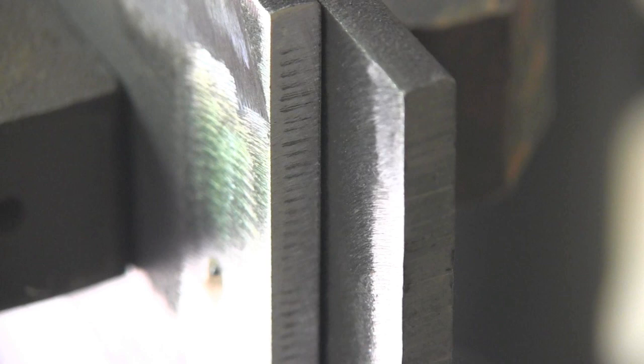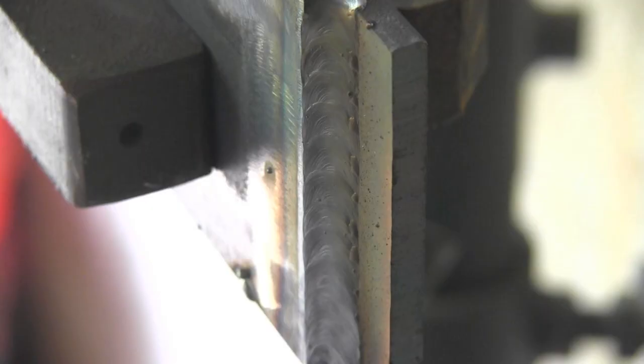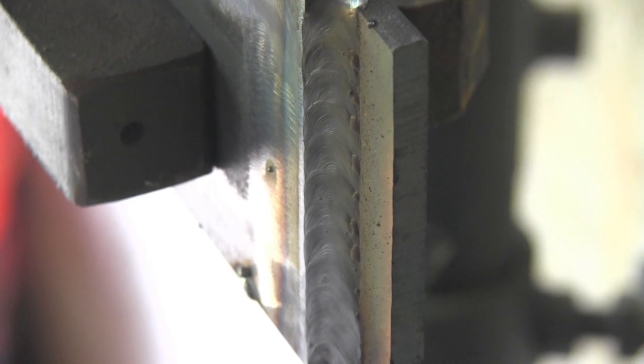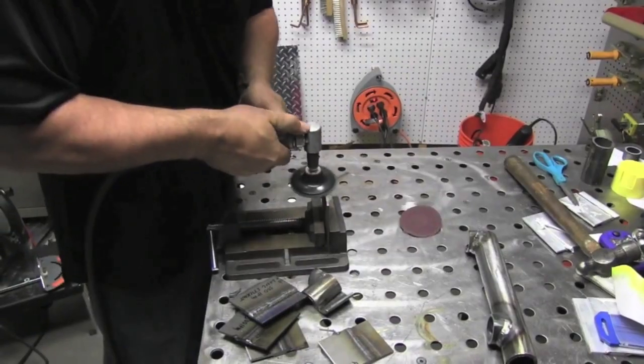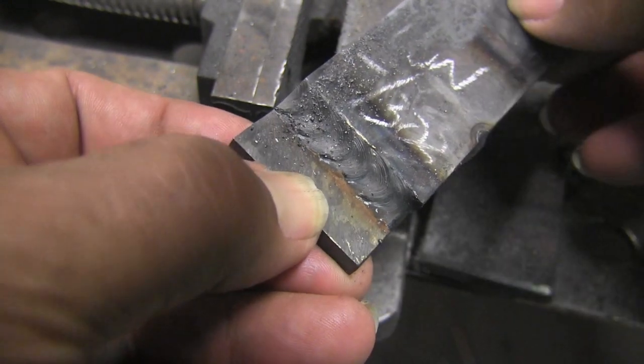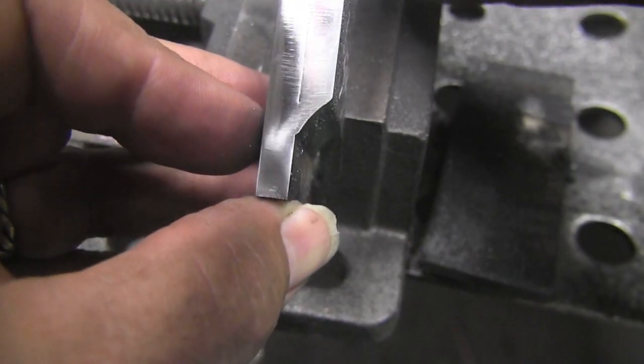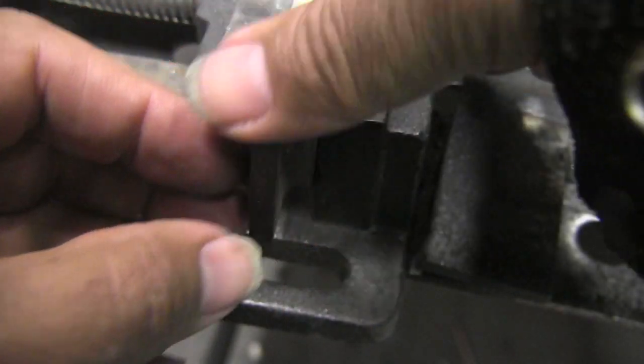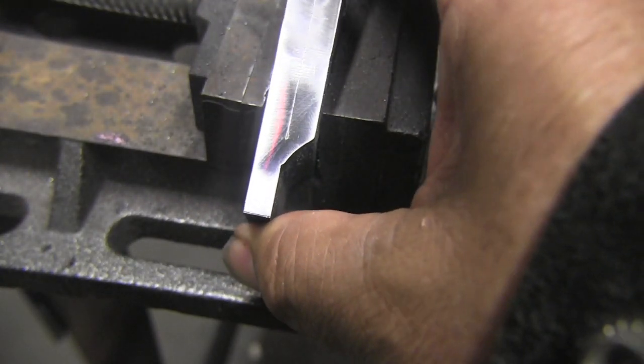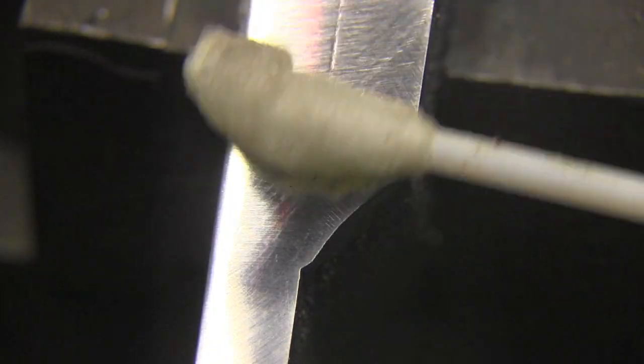Well, let's take those same settings and same machine, and now let's clean the metal and weld downhill and see what the difference is. All the mill scale has been removed, and again, I'm using the same exact settings. I'm trying to just go fast enough to stay in the front of the puddle. Makes for a decent looking weld, but still with any downhill weld like that, you kind of wonder if you got all the way down into the root of the joint. So we're going to polish and etch it here, and we'll see exactly how far it penetrated in just about 2 seconds.